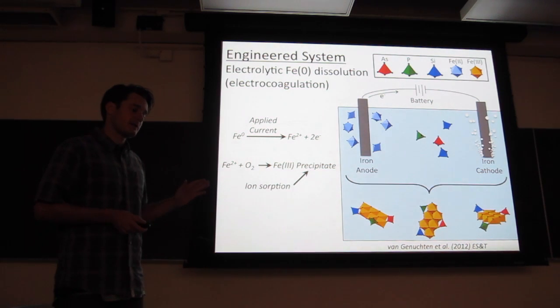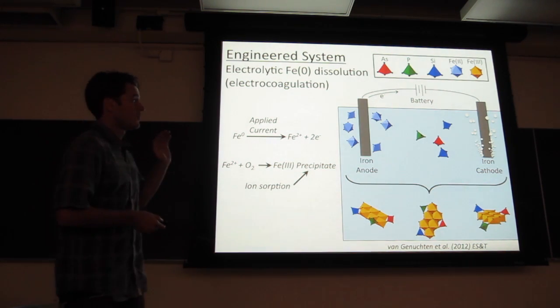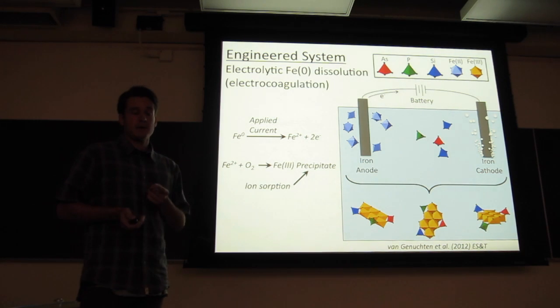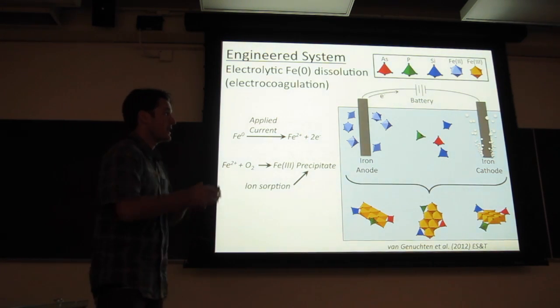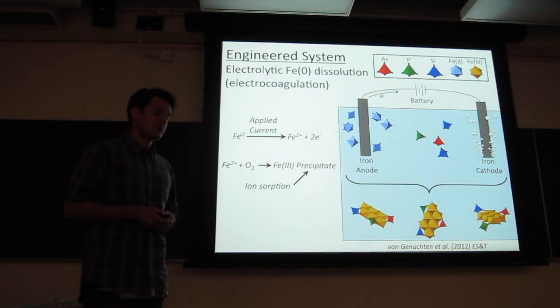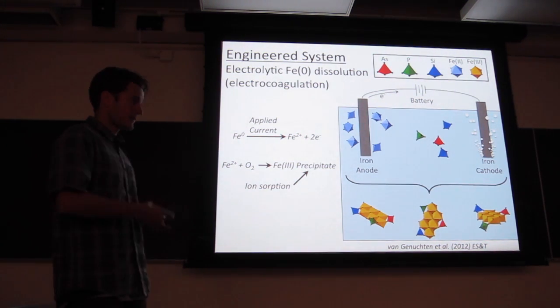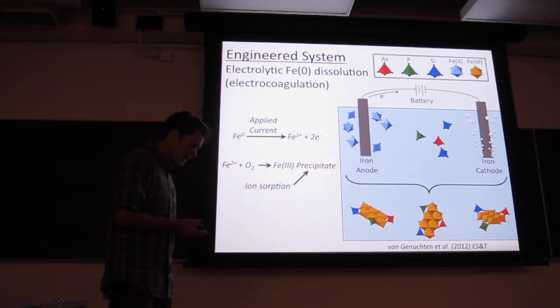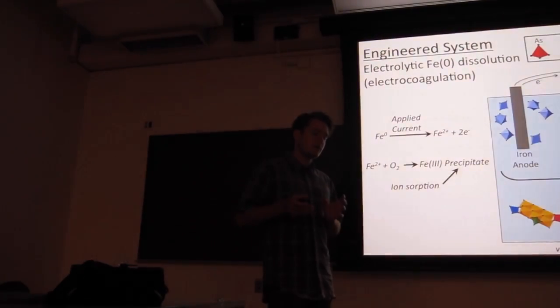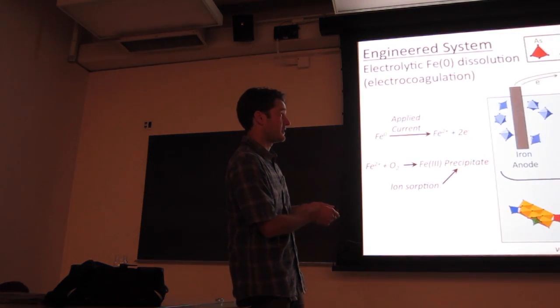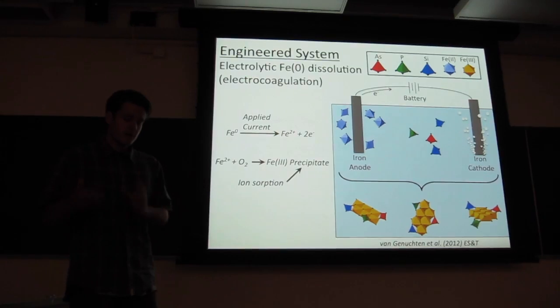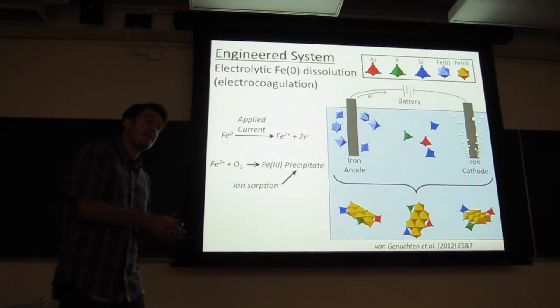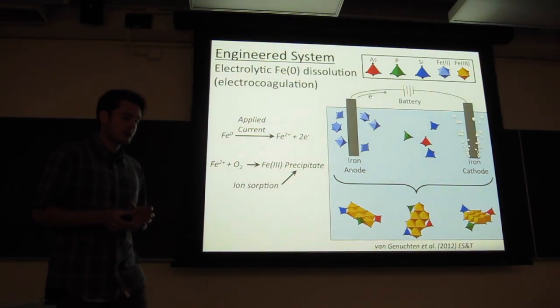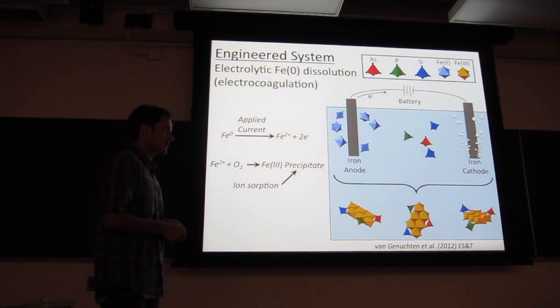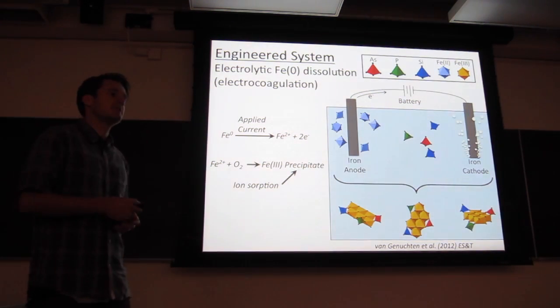the technical process that I'm going to focus on mostly is that we're generating iron essentially one atom at a time, and we're generating iron precipitates in the presence of these co-occurring ions. And so groundwater doesn't just contain arsenic, it contains silicate, phosphate, calcium, magnesium. And it's the interaction of these oxyanions, like what I'm showing here, arsenic is in red, phosphate in green, silica is in blue. It's the interaction of oxyanions with bivalent cations that can change the structure and reactivity of iron oxides. And that ultimately governs the performance of EC systems in the field.